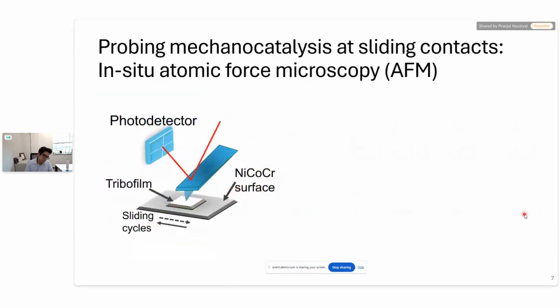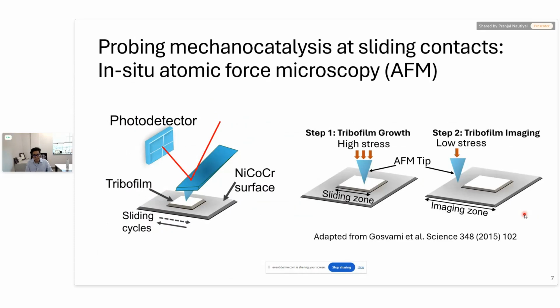And then to study the catalytic properties of nickel, cobalt, chrome, we used in-situ atomic force microscopy approach. So in this method, we use a sharp diamond tip, and we use that tip and we scan over the nickel, cobalt, chrome alloy. We apply very high contact stresses. We raster over the alloy over a predetermined area. And then because of the stresses, we hypothesized that nickel, cobalt, chrome will catalyze the formation of a tribofilm. So as the experiment proceeds, we stop intermittently. We take larger area scans so we can actually visualize the growth of tribofilm and quantify the thickness of tribofilm as a function of scanning time. So that's the protocol. This is the same method that was developed at UPenn in Rob Carpick's lab when they showed the growth of ZDDP tribofilm for the first time.